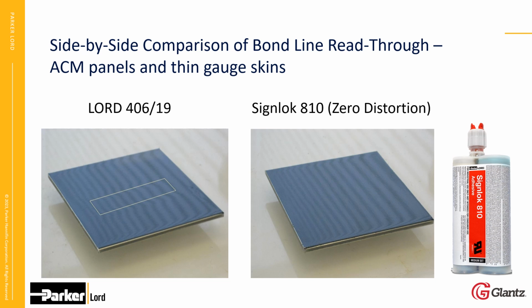This is the Signlok 810. It was designed for the sign industry. The 406-19 is really good, but on really thin gauged ACM, where the outside panel is a really thin aluminum, this adhesive works by creating heat before it's chemically bonded to the material, and that thin plastic material on the inside of the ACM can be affected by that heat and show read-through, which is basically a wavy line on the back side of the panel.